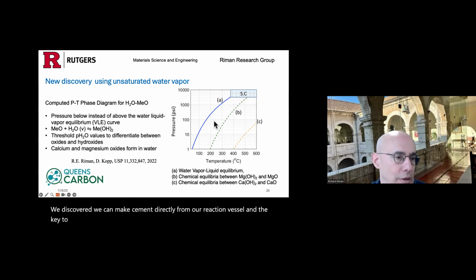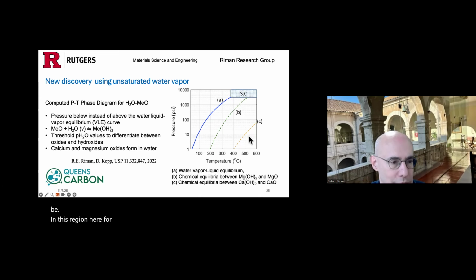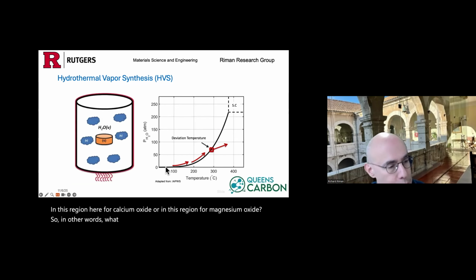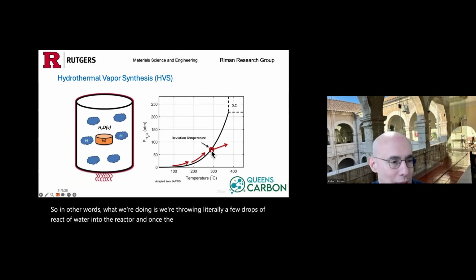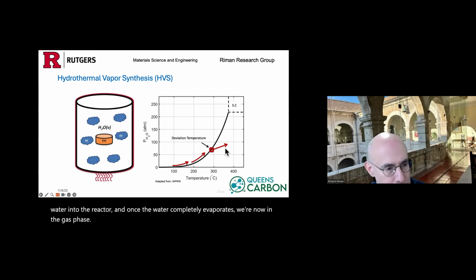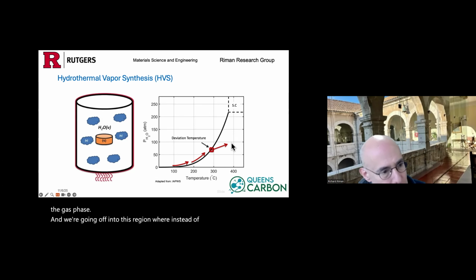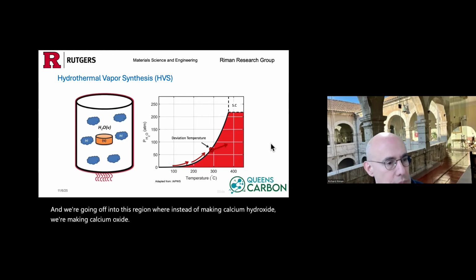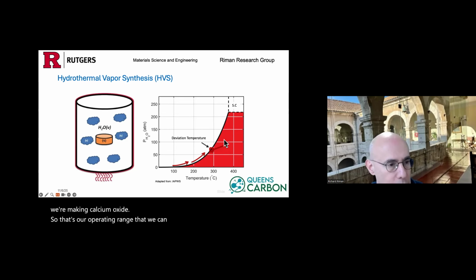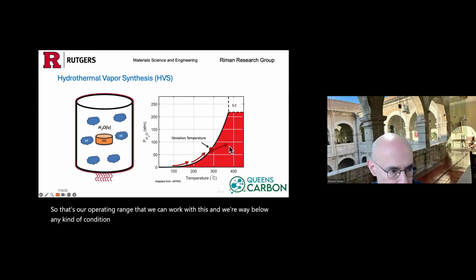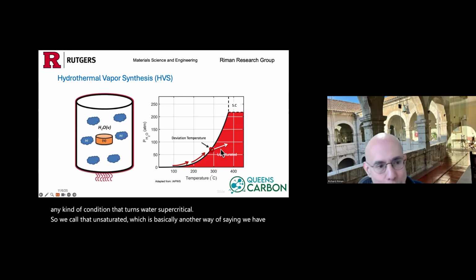And the key to doing that is getting the water partial pressure low enough that we can be in this region here for calcium oxide, or in this region for magnesium oxide. So in other words, what we're doing is we're throwing literally a few drops of water into the reactor. And once the water completely evaporates, we're now in the gas phase. And we're going off into this region where instead of making calcium hydroxide, we're making calcium oxide. So that's our operating range that we can work within. And we're way below any kind of condition that turns water supercritical. So we call that unsaturated, which is basically another way of saying we have very low relative humidity.